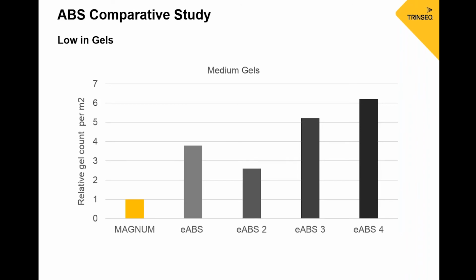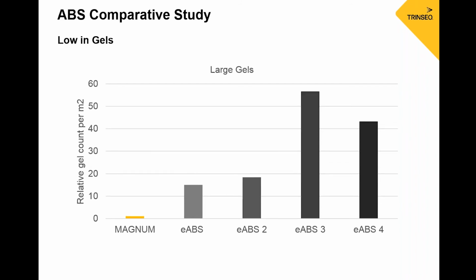So we wanted to quantify that, and this is data that's normalized to the Magnum 3904. So you can see here with medium gels, anywhere from 2.5 times to 6 times as many of the medium gels. And then with larger gels, it even becomes more prevalent. So 15 times to a little over 50 times the level of gels that we see in our Magnum 3904 product. So it can be very important for many reasons, but I wanted to share this information as it could be beneficial if you're experiencing process inconsistencies that could be related to this, or you could be getting surface defects that you want to eliminate.